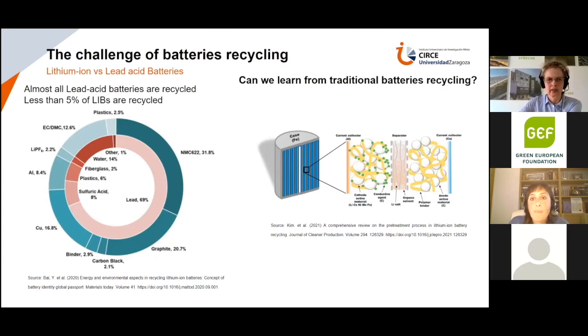Yet, a typical lithium-ion cell consists of 4 main components: the cathode, the anode, the negative electrode, a separator, and an electrolyte. And most of the critical materials are in the cathode, yet they are only one small part of the whole composition of the battery. This battery is an example of an NMC 622, but you see here it's 31.8%, whereas here the lead is almost 70%.